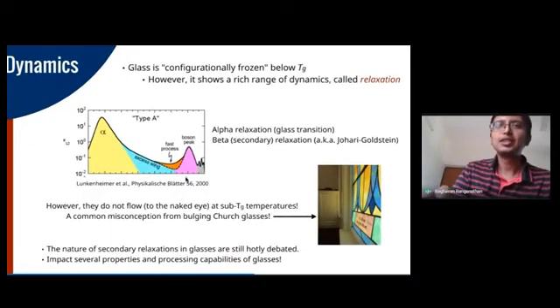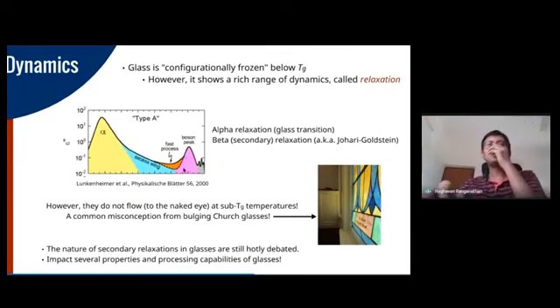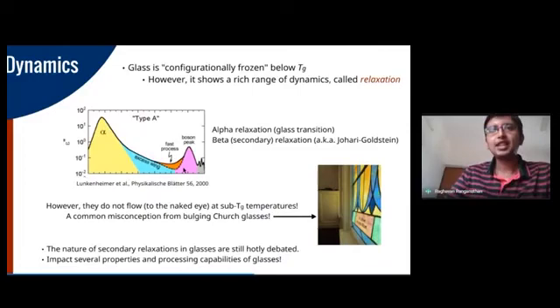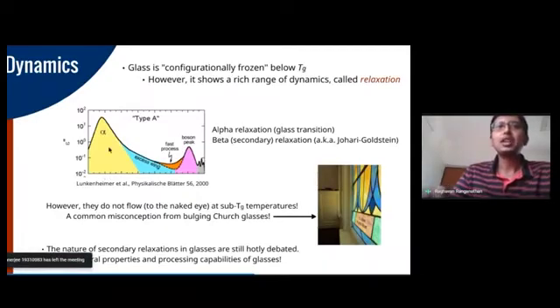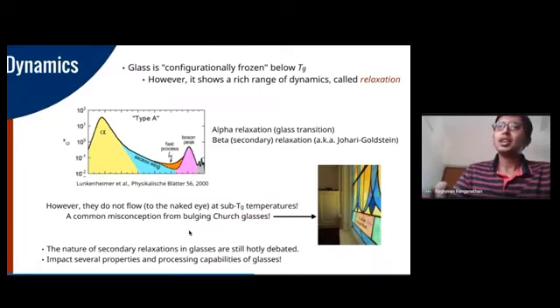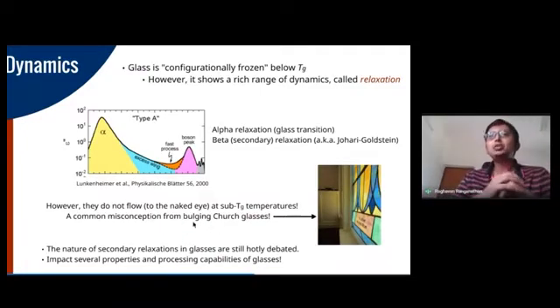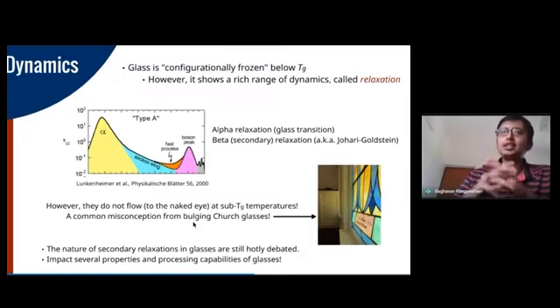Okay. So the boson peak, for instance, is a very interesting fluctuation in the glass dynamics, and this happens at the order of terahertz frequencies, so 10 power minus 12 seconds. That's the very rapid motion that the glass atoms exhibit, and this goes all the way to very, very low frequencies of the order of maybe 10 power minus 5 hertz or so, and these are the alpha relaxations that we know of, and that's the glass transition that we are familiar with. So these dynamical events do happen, but at a very short length and time scale, and they're very hard to see with the naked eye.